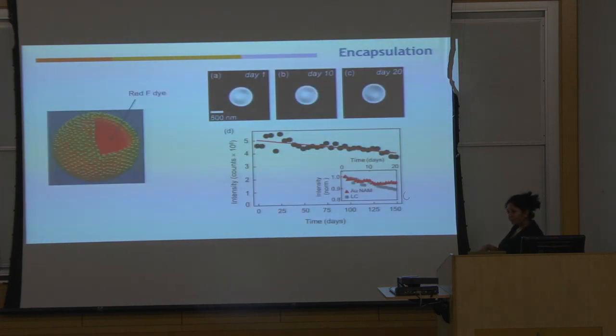So since we could form these shells, the next thing we thought is maybe we can put stuff in them. When you see something hollow, your first instinct is to stuff it with something. That's how we came up with Thanksgiving. So we put red dye inside the shells. How do we put the dye? We just mix it with the liquid crystal, and it grows, and it encapsulates the dye within.